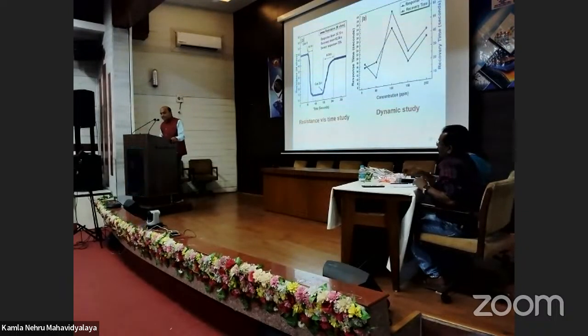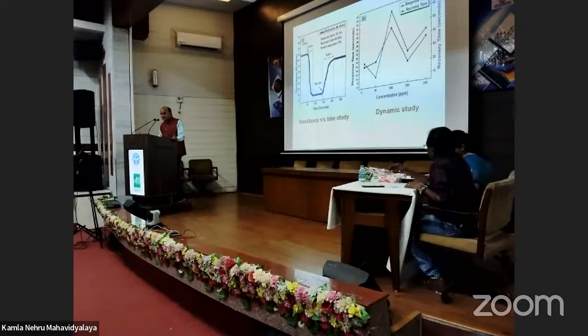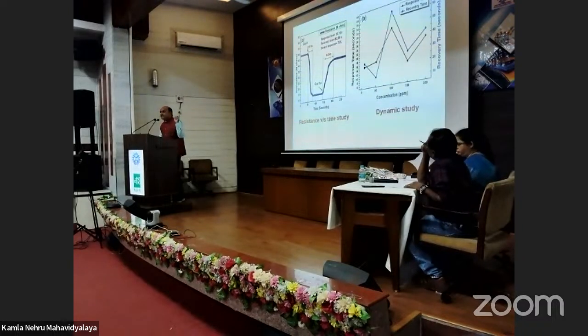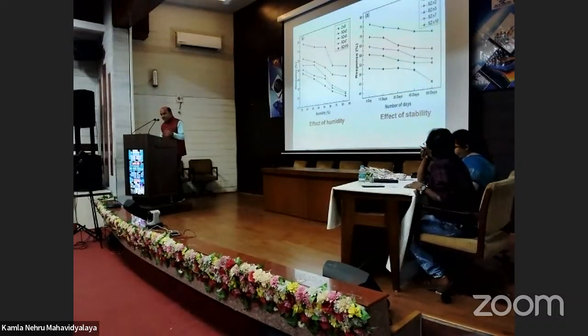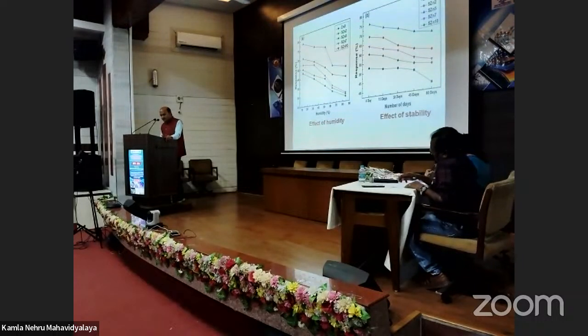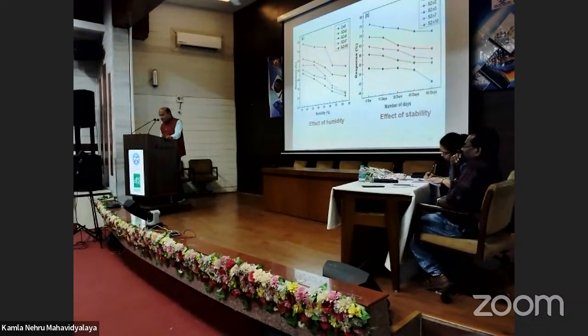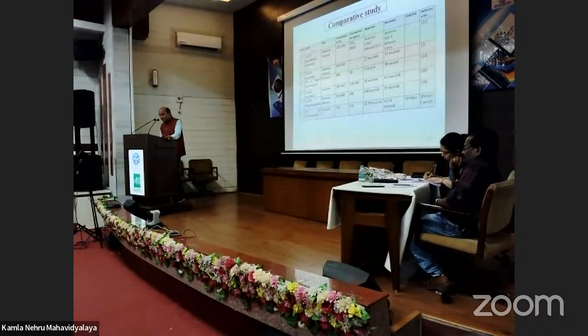Here is the gas response: response time 30.90 seconds, recovery time 63.54, and overall the sensor response is 75%. Effect of humidity we have tested, as I mentioned that the sensor should operate at various humidities, along with the stability study.